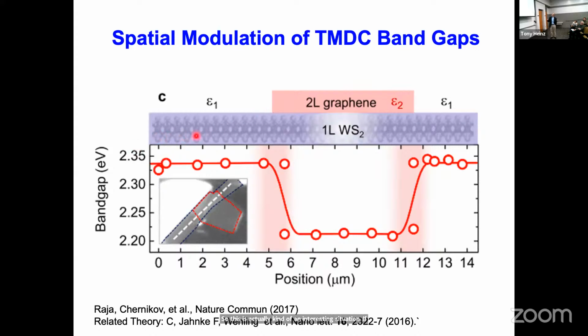If you plot then the extrapolated band gap, where you have this semiconductor monolayer and you go under a piece of graphene, then the quasi-particle band gap goes from about 2.35 eV down to 2.2 eV. So just by putting something on top of it, we've created a lateral confinement of the electrons. Now, this is actually something that's not that easy to do otherwise. Of course, there are electrostatic methods that you might use, and there are classical things like doping, but that's pretty hard to control. So this, to my way of thinking, is a distinctive feature that emerges just because the dimensions are so small that you really can't decouple the local electrostatics.